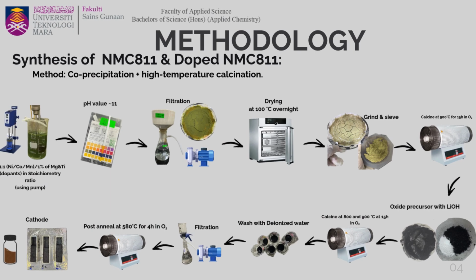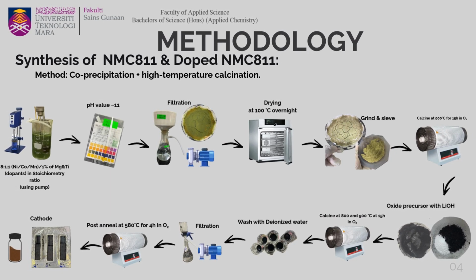So for this study, we use co-precipitation method followed by high temperature calcination. So first step, nickel, manganese, and cobalt sulfates were mixed in an 8:1:1 molar ratio. And for the doped sample, magnesium acetate tetrahydrate and titanium methoxide were added at 1%, and the pH was maintained at 11 using ammonia and sodium hydroxide, and then filtered, dried, ground, and calcined with lithium hydroxide. And then post-annealing was done at 580 degrees Celsius to improve the crystallinity. So 4 samples were prepared: pristine NMC, magnesium doped, titanium doped, and the combination of magnesium and titanium doped.